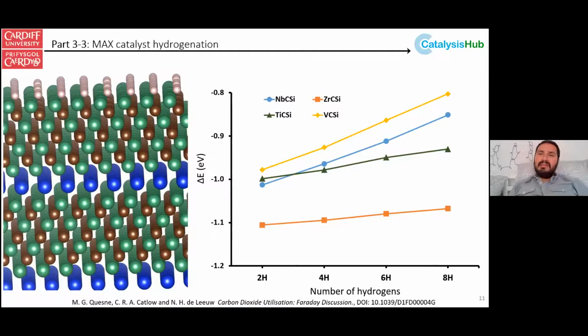So you can imagine if you look at a Brønsted-Evans-Polanyi-style volcano plot, where on one side you have the penalty being the hydrogen evolution or the hydrogen release, and the other side the exothermicity of the product formation. The product formation has to be very, very exothermic to get over this barrier. So this is probably kinetically not feasible. Although hydrogen activation is very feasible, having the hydrogens available for further reduction seems to be not so good on the pristine surfaces.